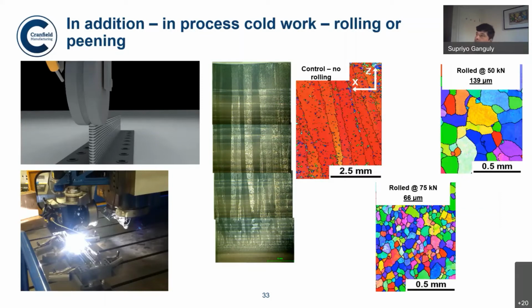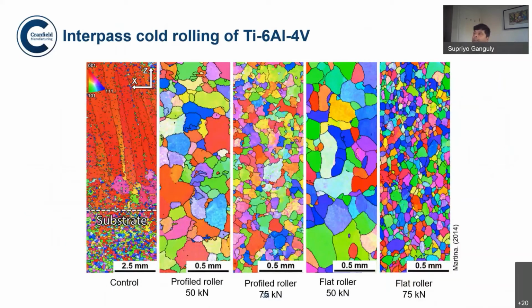This is the kind of work that makes it possible to bring this technology close to the manufacturers, because it is possible to get strength close to the wrought alloy. So this is what I will be showing now: different types of roller we tried, a profiled and flat roller, and you can see the different levels of grain refinement that can be achieved as compared to the extreme left-hand micrograph, which is showing just dendritic epitaxial growth of grains.